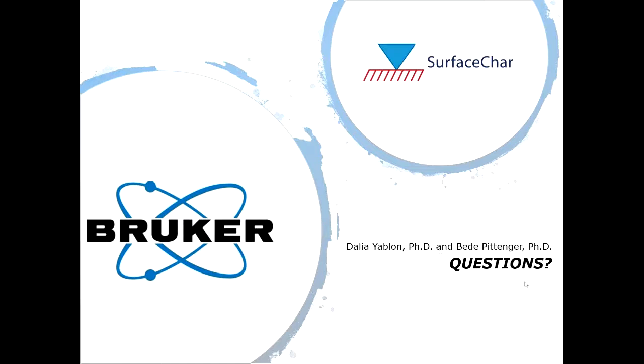That's a very good question, and I think there is a lot of potential for very interesting experiments in that realm. However, doing the measurements in liquid adds some complexity that we didn't want to take on in the initial release of this product. So we have not done much with extremely soft materials. We have done down to around a couple of megapascals currently. We expect that this will work into the kilopascals if the adhesion is not too high, but maybe not down to 1 kilopascal. That is very difficult to avoid adhesion at that point.